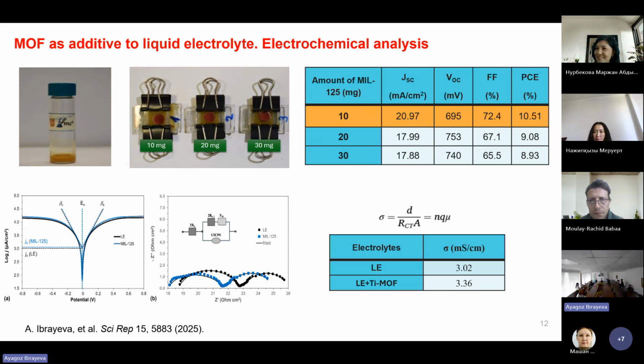Performance is decreased. That's why we chose 10 milligrams as the best one, and continued working with this device. The smaller amount of MOF is less efficient. 5 milligrams was still liquid, so there were not many electrolyte properties.